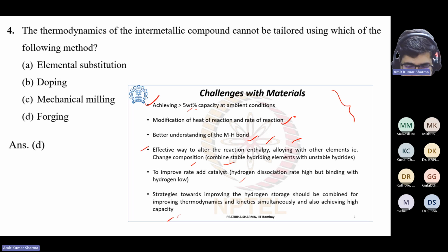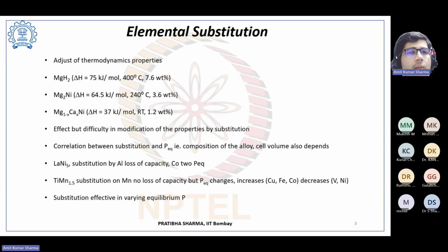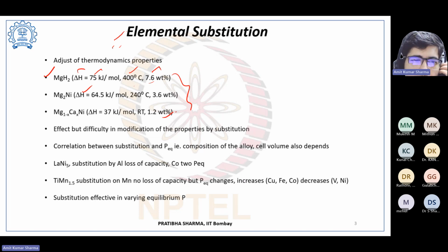So we have some methods by which we can address some of these challenges. One is elemental substitution. With this, we can adjust the properties. If you see this, it's MgH2 with delta H of 75 kilojoule per mole, 400 degrees, capacity 7.6 weight%. If you have Mg2Ni, then it's changed. Then Mg1-xCaxNi. So you can see the change. We can see the effect, but it's difficult to modify the properties by substitution. The correlation between substitution and P equilibrium depends on the composition of the alloy, and cell volume also.